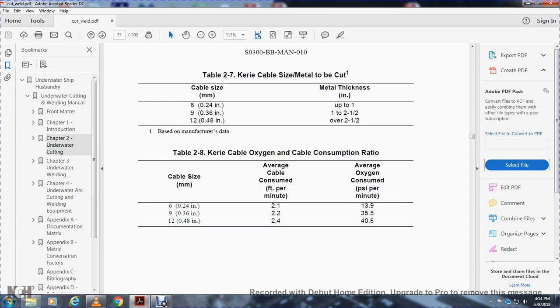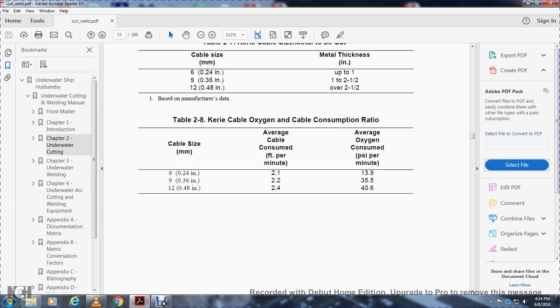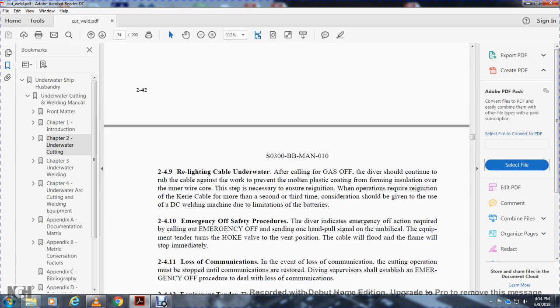Kerie Cable and oxygen consumption rates. 6mm cable: 2.1 feet per minute, 13.9 psi oxygen per minute. 9mm, 3/8 inch: 2.2 feet per minute consumed, and 35.5 psi oxygen consumed per minute. 12mm: 2.4 feet per minute of cable consumed, and oxygen 40.6 psi per minute.